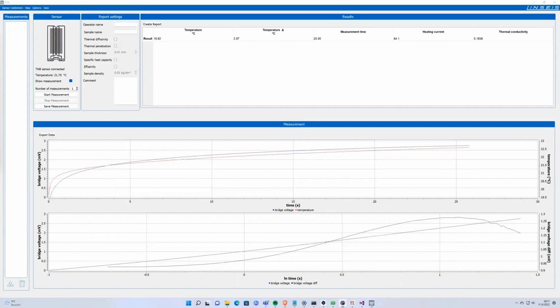So basically one can also perform some measurements manually. Here within the options, you can change the measurement time and the heating current, but the system does it also automatically. So here on the top, first sample information are typed in. Now start was clicked. Here on the bottom, you see a short waiting time for stable temperature. Let's pause this. Here on the lower left, you see trying to find optimum heating current.